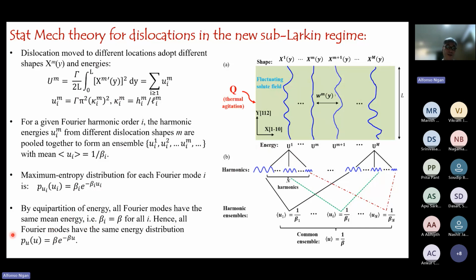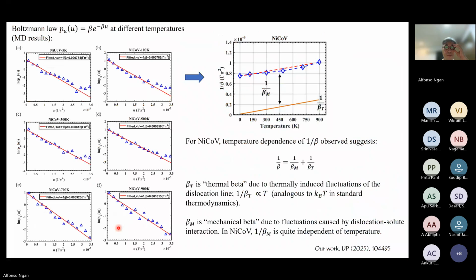So the basis of the StatMech theory for dislocations would be this unified distribution of energy, which is basically the Boltzmann distribution, which of course was confirmed by our MD simulations as we have seen just now. So again, this is to show that the Boltzmann distribution is observed, and it is observed not just at low temperature like 5K, but at high temperatures like 300 and 700 as well.